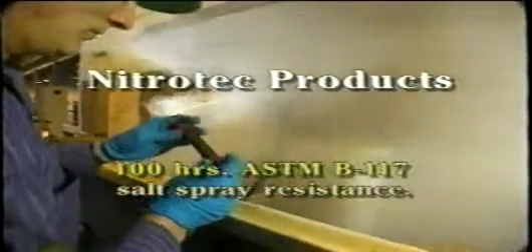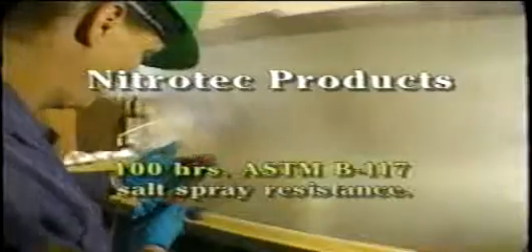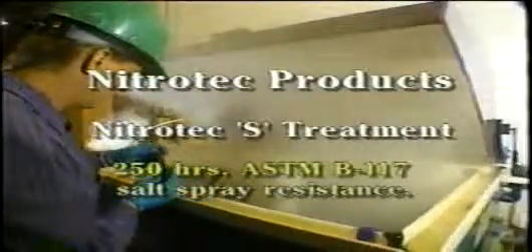Beneath the iron nitride wear layer is a nitrogen-enriched diffusion zone, a light, shallow hardened case which provides excellent support and dent resistance to the wear layer without creating the machining difficulties inherent in induction-hardened products. Nitrotec process products offer well over 100 hours of ASTM B117 neutral salt spray corrosion resistance. A second polishing and oxidizing sequence, the Nitrotec 'S' Treatment, can give over 250 hours of resistance.